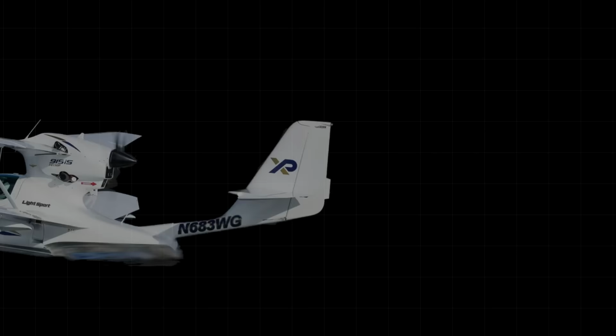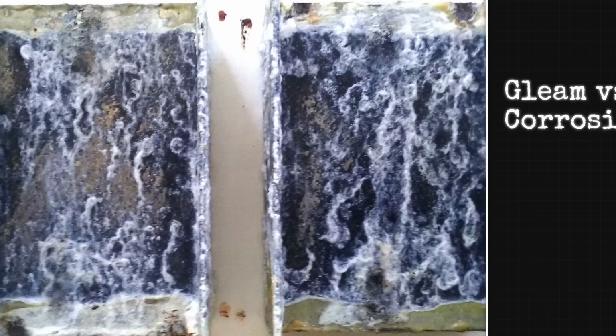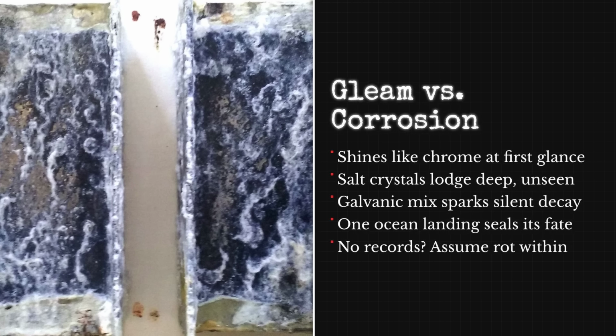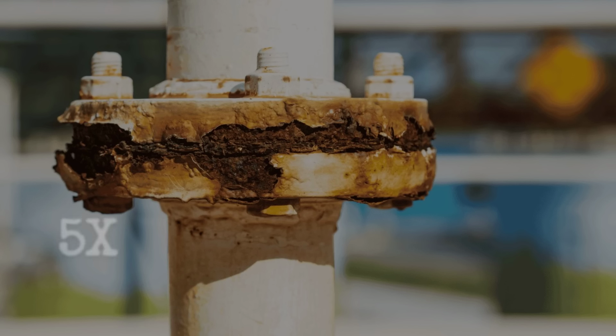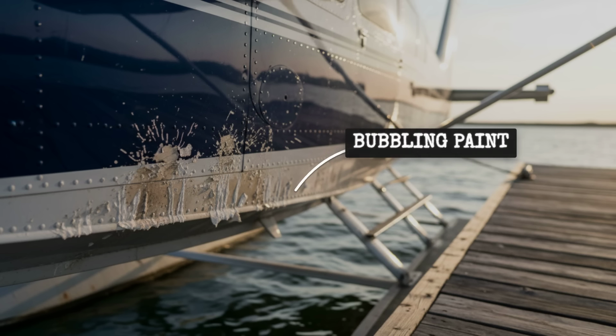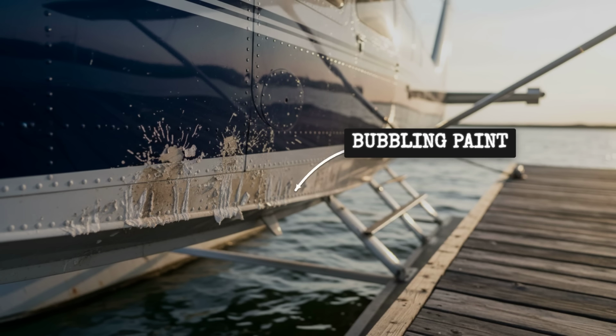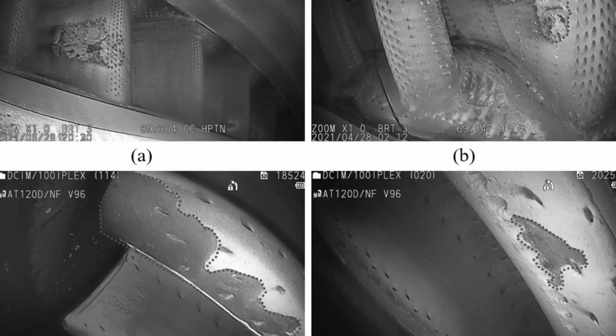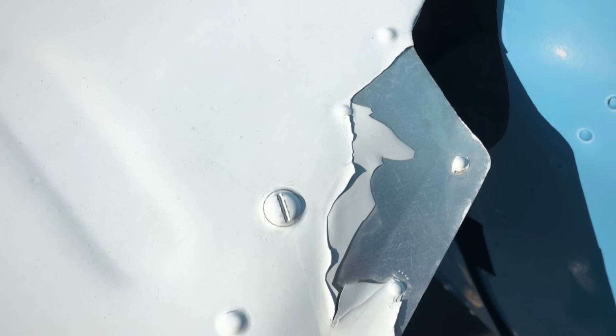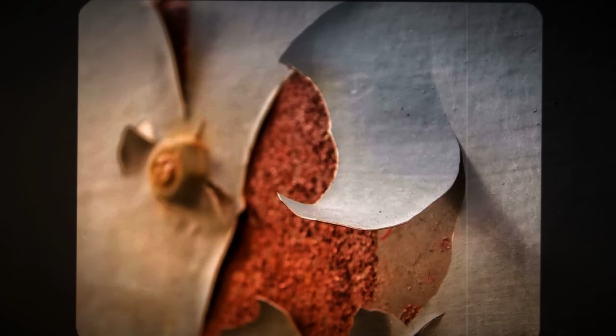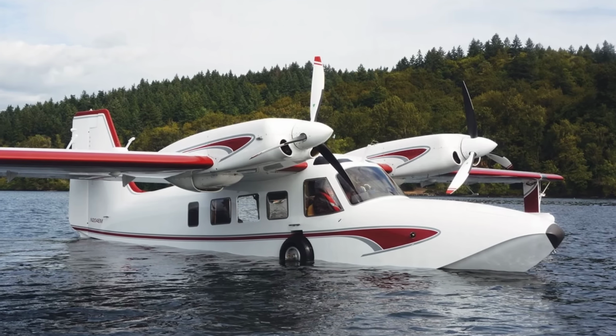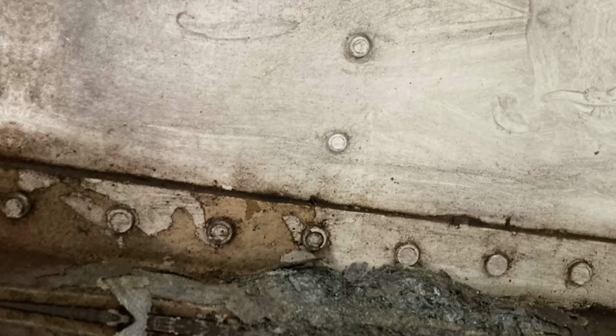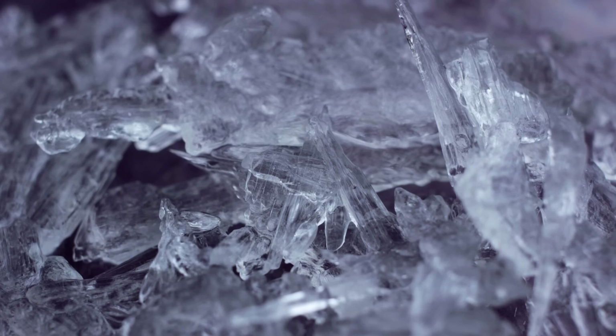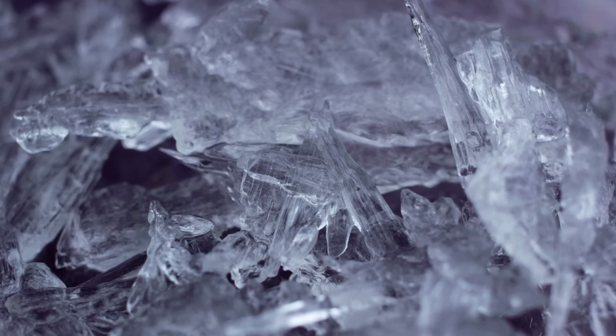Salt does not just attack one metal, it turns the entire airframe into a battery. Aluminum, magnesium, steel, throw them together with a little moisture and a pinch of salt, and the corrosion races through every joint 5 times faster than in fresh water. You might spot a little bubbling paint or a white streak here and there, but by the time you see it, the damage is already deep inside. The seams swell, the rivets loosen, and the metal flakes away under the skin. There is no easy fix. No quick flush or magic spray will undo years of neglect. Once the salt is in the seams, you cannot get it out.